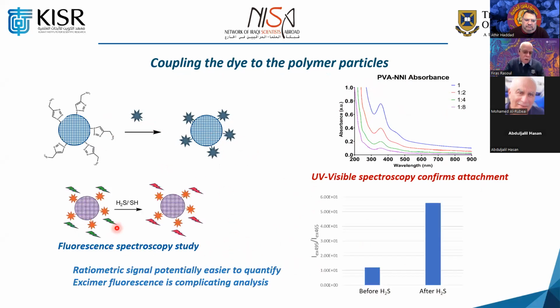And also we looked into the fluorescence by exposing it to H2S. This is non-fluorescent, and it becomes fluorescent. Because of the broad peak, and because of the high concentration of these functional groups and the level of fluorescent dye inside and outside of the nanoparticle, because this nanoparticle is porous, we found it is very, very difficult to directly measure the signal coming from the fluorescence, because there is a lot of interaction and there is a lot of excimer fluorescence coming up.